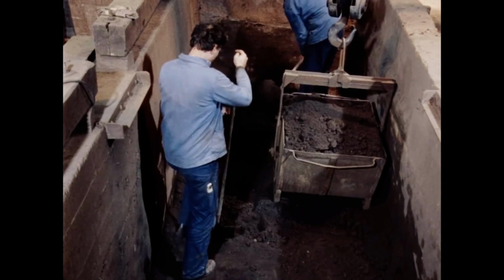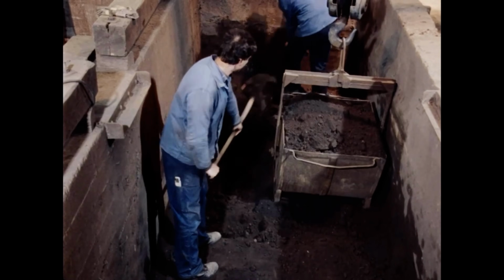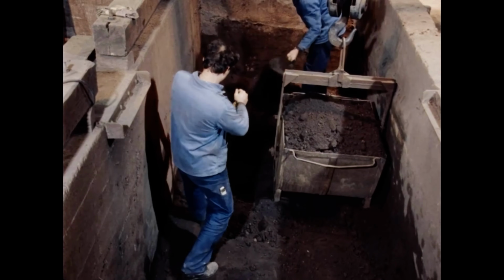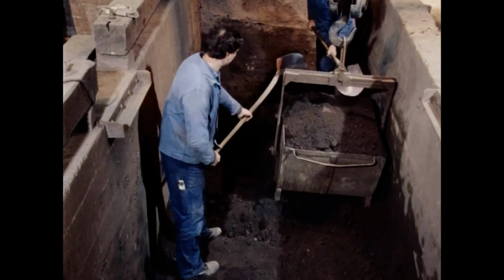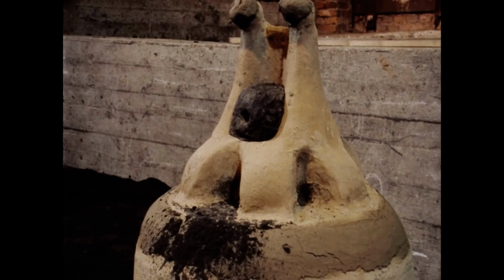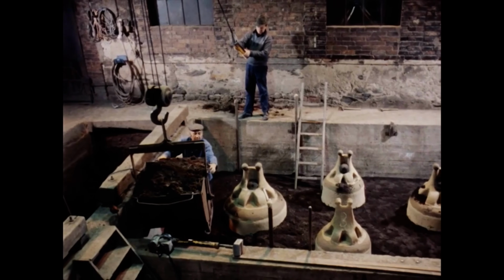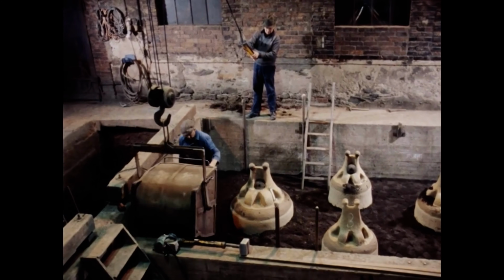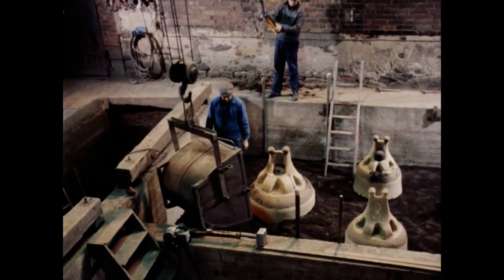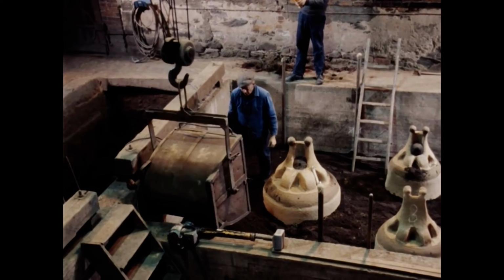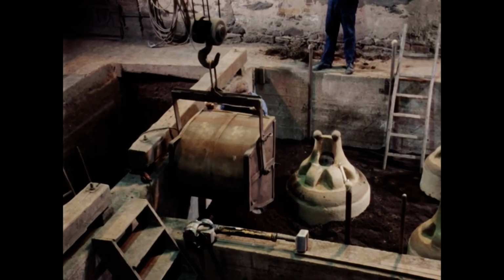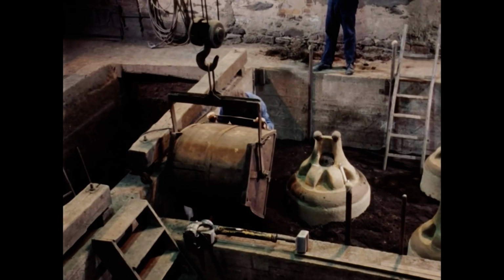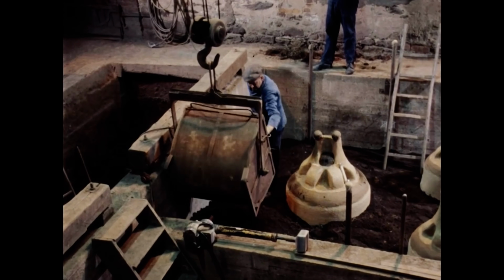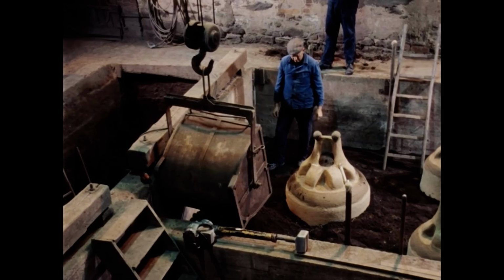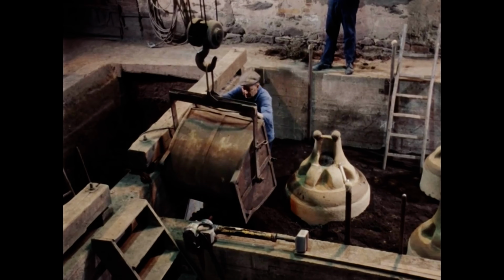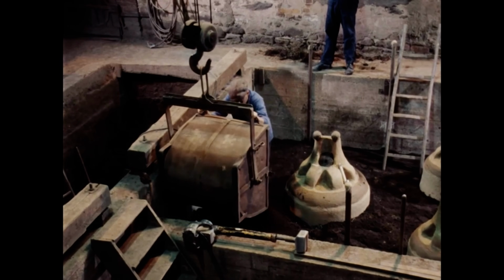After the molds are in place, the casting pit is filled with topsoil, which the molders take from a side pit. The excavation takes place in 20 centimeter deep layers. The number of earth layers is noted with chalk marks on the pit wall. As Master Bell founder Mr. Mabalon emphasizes, they use pure topsoil, which becomes as hard as concrete due to the casting heat, and thus prevents the casting pressure from bursting the shell.